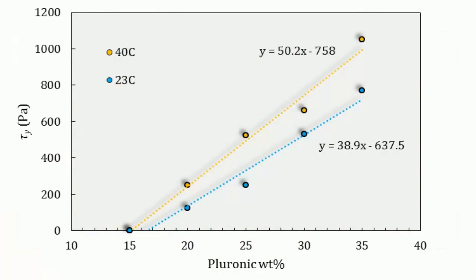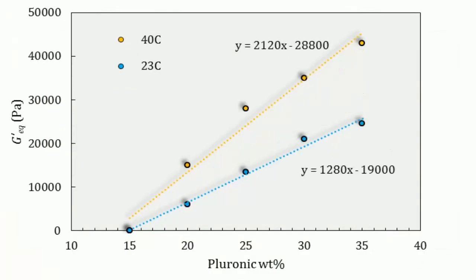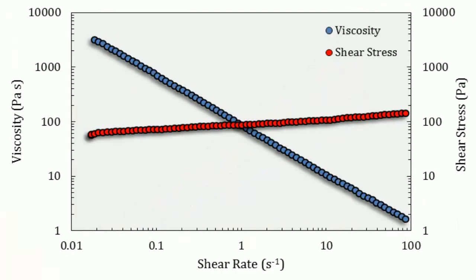It really did. Getting the printing parameters right is important, obviously. Choosing a paste with high powder content, selecting the right print speed, faster is generally better if the paste stability allows it, and getting the spacing between the extruded filaments just right. The source found you actually need a little bit of overlap between adjacent lines or filaments. That helps squeeze them together and eliminate gaps between them.